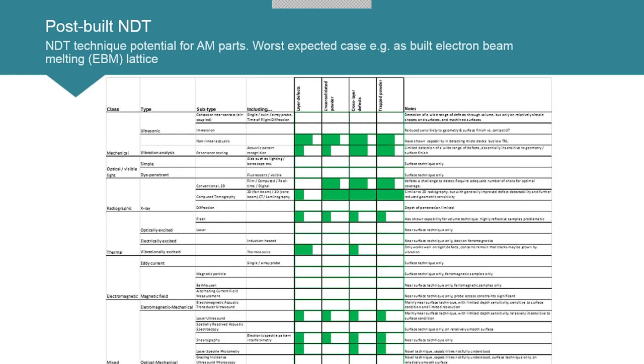So typically, electron beam melting is rougher than laser powder bed, and there is also geometrical complexity. So here we put the worst case that we believe it is, lattice structures. So this is the worst case scenario basically. But it's a matrix which we generated also for our AM, and depending on the level of surface roughness and geometrical complexity, it will give you different outputs.